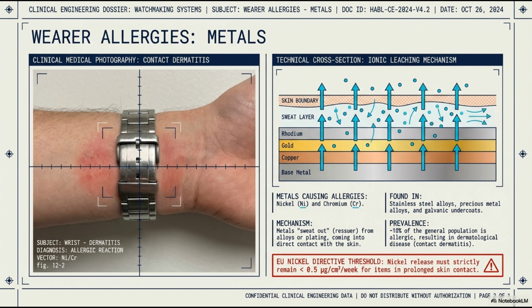Where do we find these? They are ubiquitous. They are alloying agents in standard stainless steel, they are used in precious metal alloys to alter color, and they are heavily used as galvanic undercoats before gold or rhodium plating. Look at the cross-section diagram showing the ionic leaching mechanism. The metals don't just sit there. When exposed to human sweat, which is acidic, the nickel ions literally sweat out or leach from the alloy, migrating through the plating and penetrating the skin boundary.